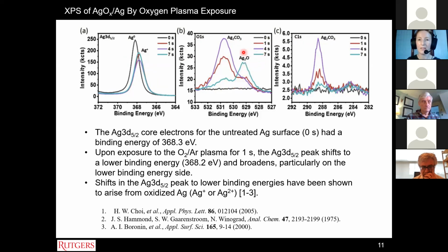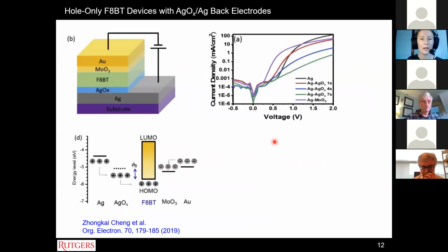And you can see for 7 seconds, we form predominantly silver oxide, Ag2O, even though that's there in actual fact for all of the cases as well. So we have some silver carbonate and some Ag2O forming on our metal electrode. And then we looked at the incorporation of these partially oxidized silver electrodes.